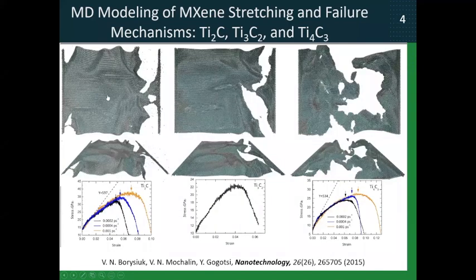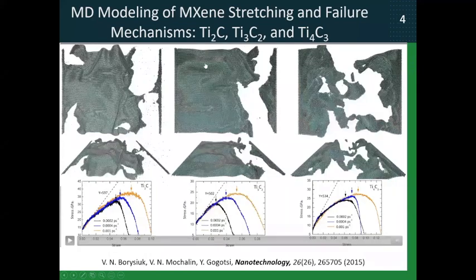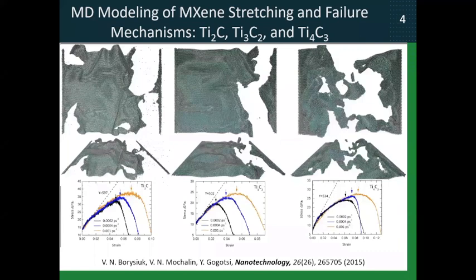And so you not only can use this modeling to get information about failure mechanisms and mechanical properties of these MXenes, but you can also use the MXenes as models of materials with precise control of monolayer thickness. So this is a very interesting aspect, which I will return to again and again in the talk, that MXenes we can also use as convenient models for fundamental studies of any property which depends on the monolayer thickness, of course, including mechanical properties.